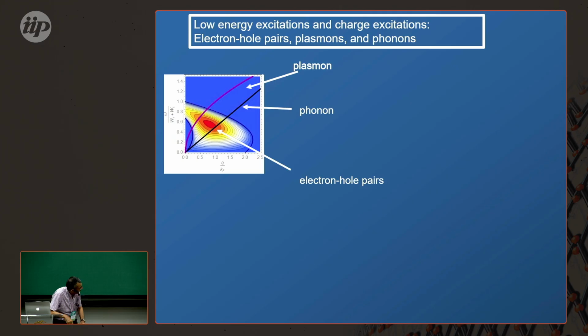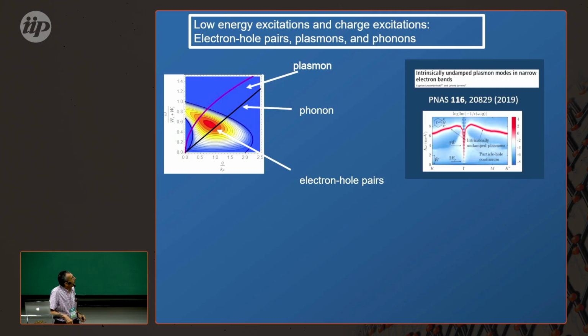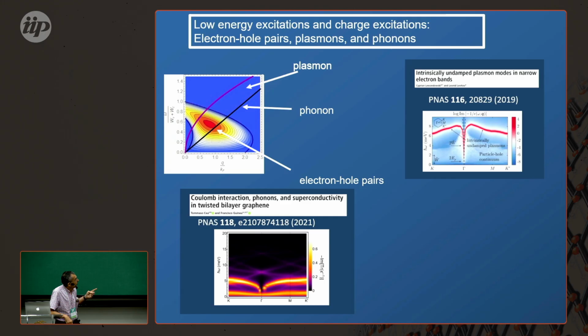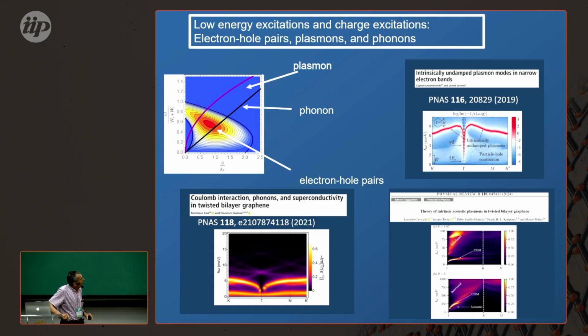This is what happens in twisted bilayer graphene. This is a calculation by Lenin Levitov and Cyprian Lewandowski. This is our own calculation where the faint blue lines are the phonons. And this is a more accurate calculation without phonons from ICFO, from Pablo Jarillo-Herrero, Marco Polini, Frank Oppens, et al., where they also found, as expected, acoustic plasmons because it's a bilayer.